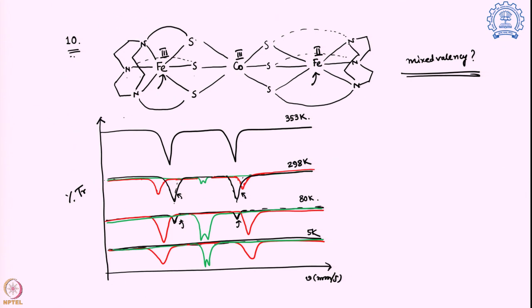How do we explain this result? In the beginning, I have only one set of data, whereas later on it splits into two different sets of data, extra peaks coming out, the red and green. The black is still staying, and slowly only the red and green remain; the black is totally gone. So what is happening? The red one and the green one, what are those? The red one is actually an iron 3 complex in low spin state, and the green one is iron 2 in low spin state.